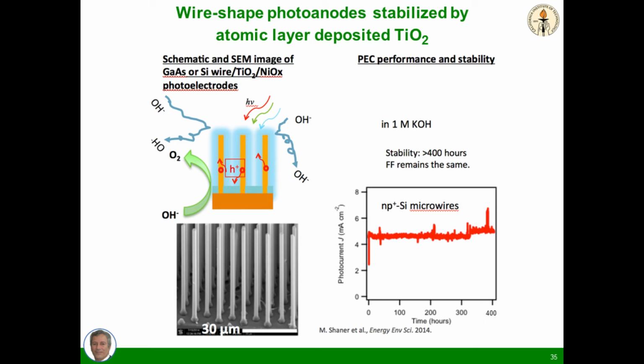But in the case of silicon, we have this self-healing array where if we have a scratch in the coating or a pinhole, it oxidizes a little bit there, but it doesn't propagate the defect because it passivates. And those are the kinds of materials, like these silicon microwire arrays, that are the best suited to this protection scheme that lets these materials be our missing piece in the top part of the puzzle.